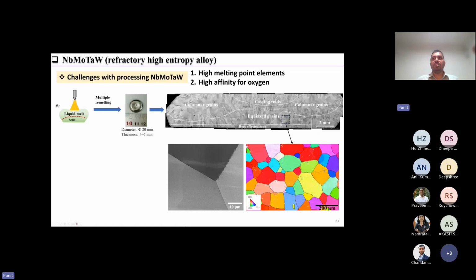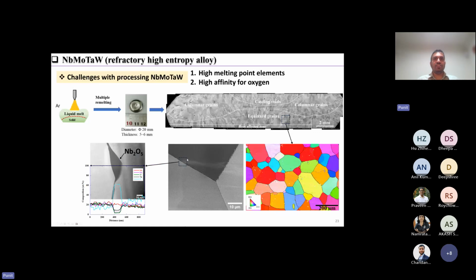Although we were able to achieve these equiaxed grains of, you can see, 2 mm in thickness and 7 to 8 mm in length, the challenge of oxygen capture we were not able to avoid. And the grain boundary had these oxide particles like niobium pentoxide, Nb2O5, or tantalum pentoxide. So we were not able to avoid the oxidation of the grain boundary or formation of oxides on the grain boundary, but we were able to achieve this equiaxed microstructure. So we went ahead and we evaluated the properties of this material under tension.